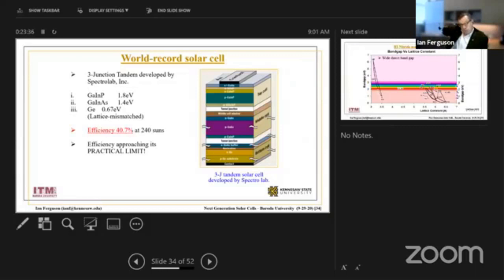The other thing is, this isn't actually showing all the layers in here, but once you go up to something where you want these higher efficiencies, and if you have four junctions in here, you may have a hundred different layers, and it may take you ten or twelve hours to grow this crystalline structure in the material.